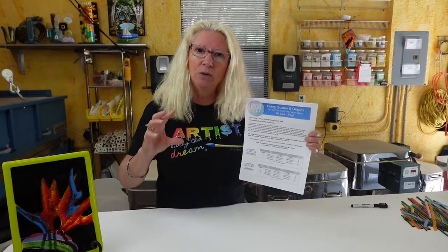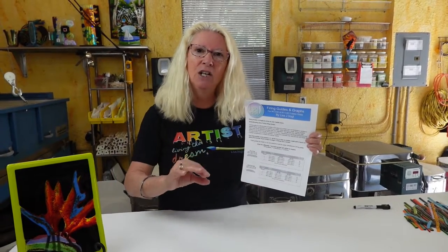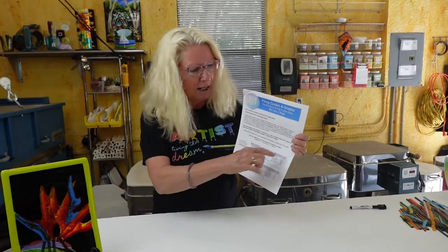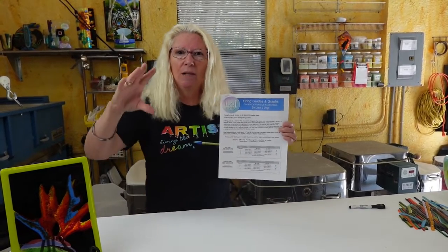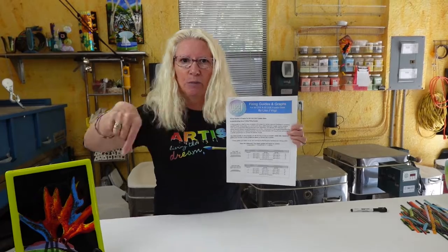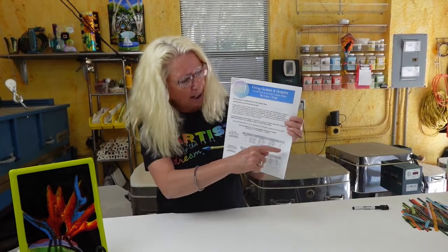Bubble squeeze is where you make all those different layers uniform in temperature to reduce any bubbles that might otherwise be trapped. If you go faster and you don't have this hold time, what can happen is the top layer will seal to the bottom layer around the perimeter like a suction cup. Air becomes trapped between those layers, and it can show up in your project in the form of tiny little bubbles. So by having this hold at 60 minutes at 1,300 degrees, you'll minimize the effect and the amount of those bubbles.